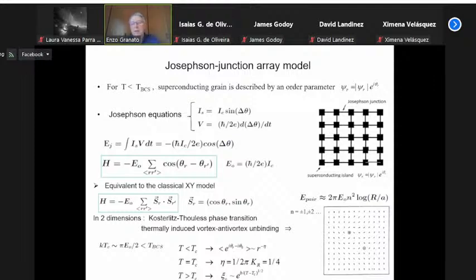So the Josephson junction array model is basically a system, as illustrated in the figure on the top right, of an array of superconducting grains coupled by the Josephson effect. If the temperature is below the critical temperature for the superconducting transition in the grains, the T_BCS here, you can have a Josephson effect between the grains. And this Josephson effect is characterized by two equations, the current relation and the voltage relation. The current relation says that between the grains a supercurrent can flow without a voltage, and this current is proportional to the sine of the phase difference between the phases of the superconducting order parameter which developed in the grains.